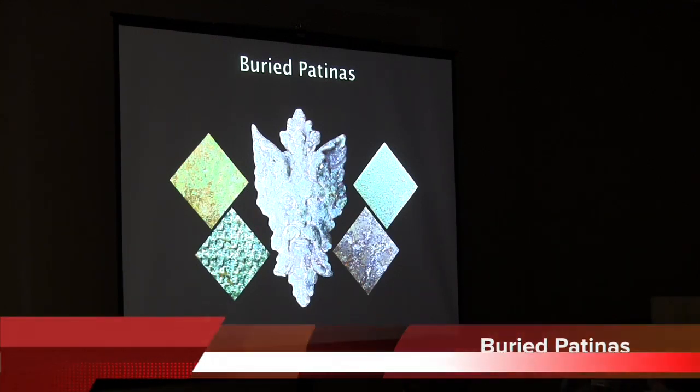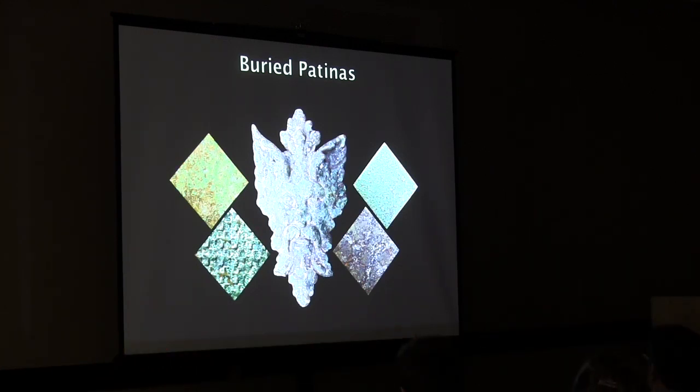We already went through this one here. Again, the sawdust is real important. That would be white pine, Douglas fir. You can put any kind of chemicals you want in it. You can use, like I said, ammonia, vinegar, salt, works great. And you want some chips as well as some very fine sawdust in there, so it has room to breathe. You need oxygen in there. This one, I used Tiffany green, number one.